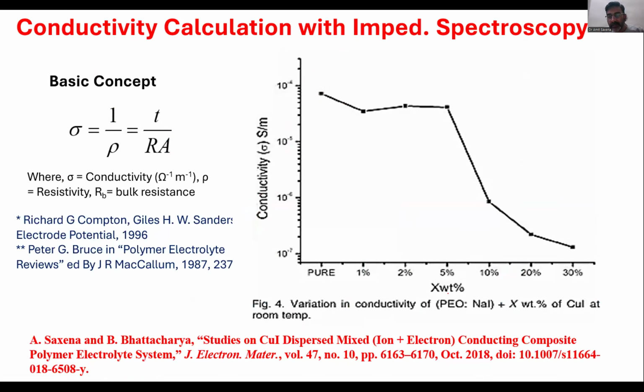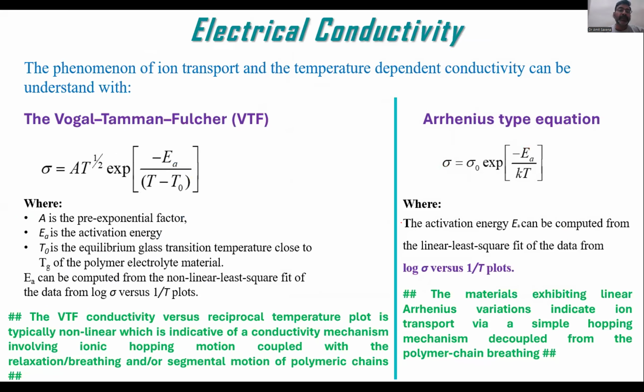Like you can see that when I enhance the concentration of CuI, the conductivity initially dropped to a very extreme value, starting from 10 to the power minus 4 and dropping down to 10 to the power minus 7. So what is the reason behind the drop in conductivity? You can also understand what would be the reason behind the change in conductivity, maybe upper or maybe lower side. To understand that, we have different equations. One is the Vogel-Tammann-Fulcher equation or the Arrhenius type equation. This is to understand the conductivity of your sample.